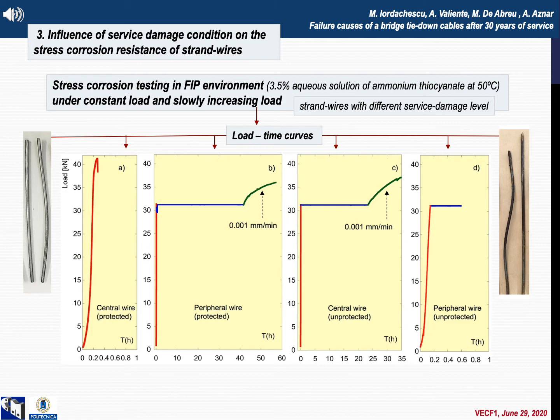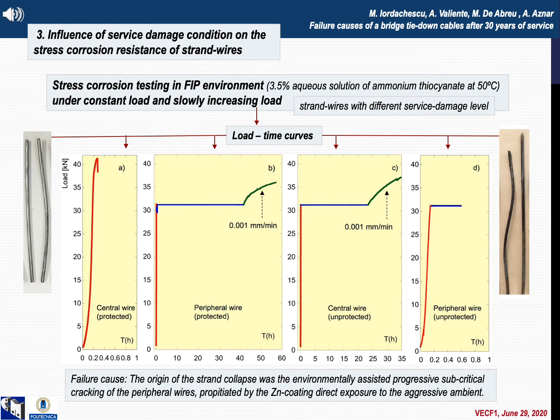The failures of central and peripheral wires in the constant extension rate tensile testing occurred for loads higher than the 31 kilonewtons used in the stress corrosion constant load test, but less than the wire's resistance capacity of 42 kilonewtons. Their premature failure being a consequence of the induced embrittlement by the FIP environment. Accordingly, the origin of the strand collapse was the environmentally assisted progressive subcritical cracking of the peripheral wires propitiated by the zinc coating direct exposure to the service ambient.